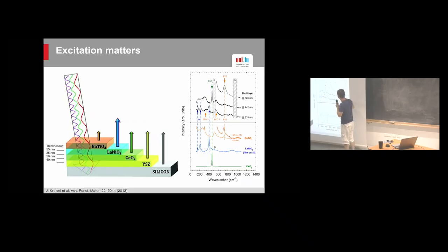Then maybe easier to understand is this one, the red laser. So red laser is clearly below the band gap of barium titanate, so you really go through, but then it gets absorbed by lanthanum nickelate. Okay, so here you hardly see barium titanate at all, but you do see, where is it? It's here. You do see the peaks that are characteristic of lanthanum nickelate. Okay, and the same thing happens for the blue laser, which is sort of in between. In that case, it's the cerium oxide that shows up. Okay, so this is a nice example.